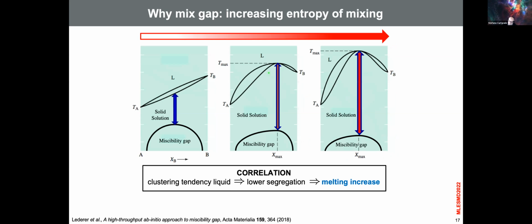Because now let's do the opposite. Let's suppose that you have a phase diagram, and the phase diagram has a miscibility gap. Okay, I'm running out of time, but please give me another 5 minutes, okay? And suppose that now you are God, and you are able to put your finger here and bring down the miscibility gap. Wow, if you bring this down, then you will bring up the critical temperature of the melting. Okay, so there is actually a correlation between the miscibility gap critical temperature and the critical point of the congruent melting.